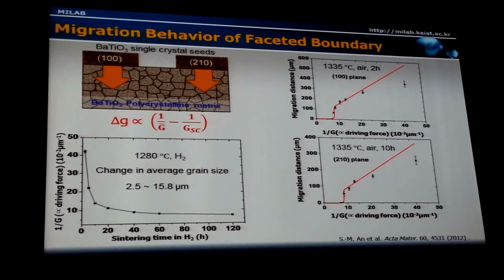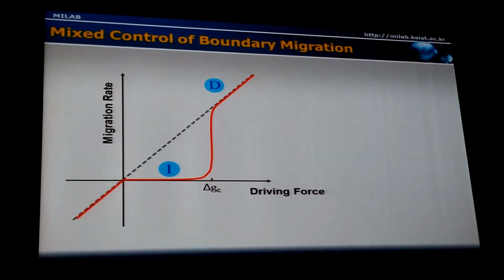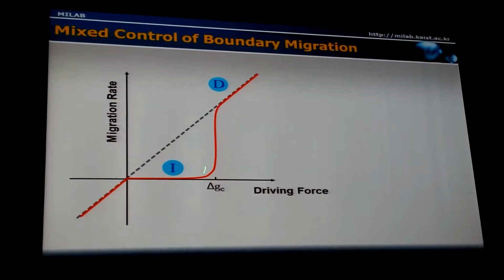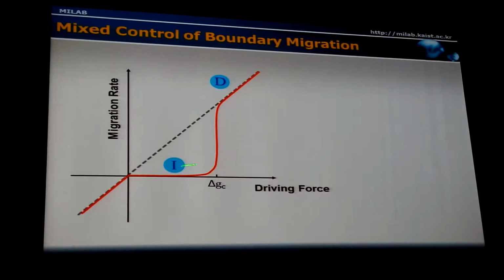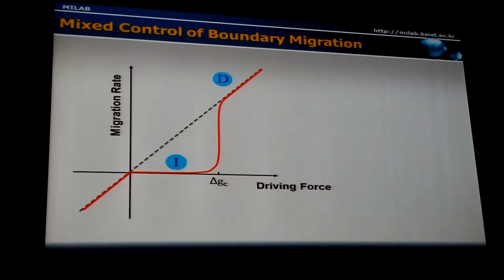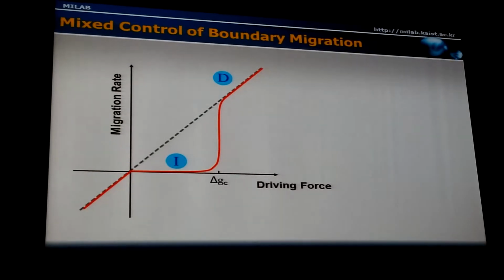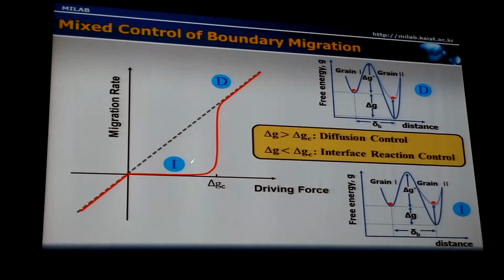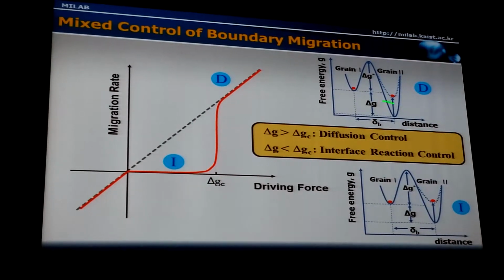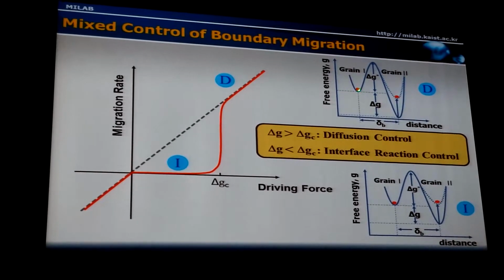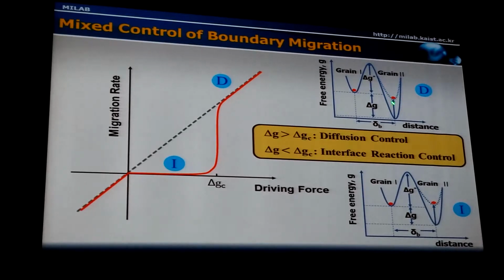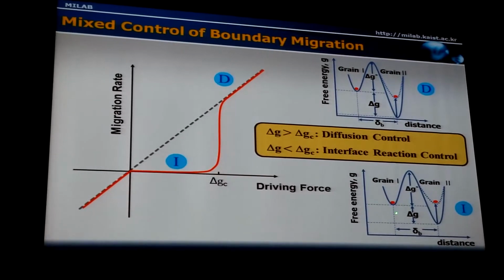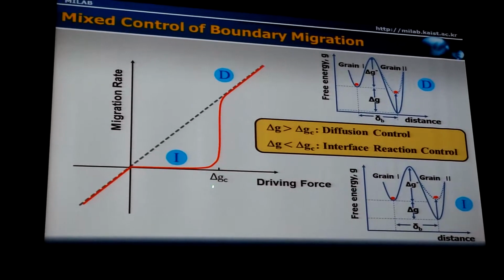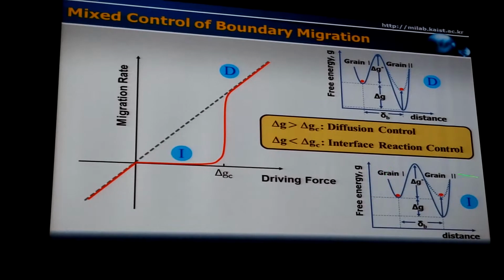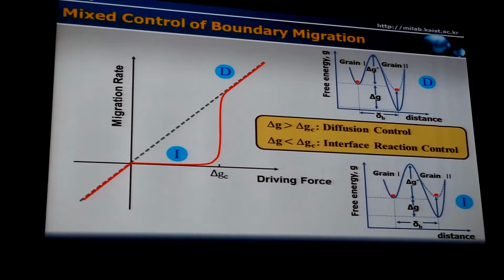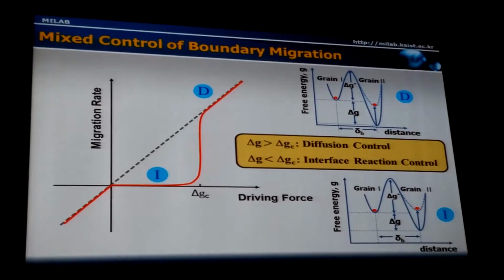So this observation and the results suggest that the migration of the boundary or solid-liquid interface is governed either by interface reaction or diffusion when the boundary is faceted or at least partially faceted. So when the driving force is large enough above a critical value, then the atoms that were transported to the surface of the growing grain remain. But if the driving force is smaller than the critical value, then the atoms will return back to the original grain, showing the interface reaction controlled growth.